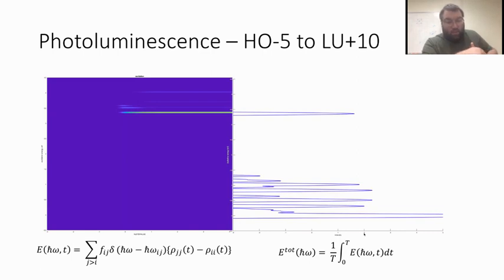And that 3.3, is it the band gap? That is the band gap. The band gap was 3.29 something. Okay. So basically, instead of emitting at the energy difference from HOMO -5 to LUMO +10, it loses energy and gets closer to the HOMO and the LUMO, or the electron and the hole get closer to the HOMO and the LUMO, and then they recombine, basically emitting at the wavelength corresponding to the energy close to the band gap, right? If I understood what you said correctly, yeah.